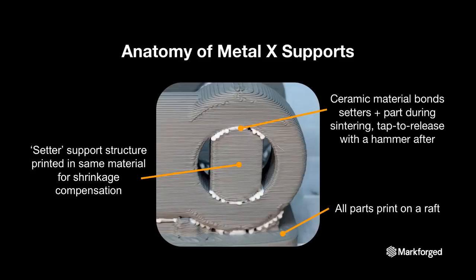So what we do is we also print a layer of ceramic material between the setter structure and the part. It allows the part to weakly bond to the supports so that everything stays together, and then you avoid any sort of dimensional inaccuracy during sintering. But it allows it to tap to release after the part is done sintering. So once it's cooled down and comes out of the oven, you can gently tap it with a hammer and it pops the supports right out. And so that's how supports work.